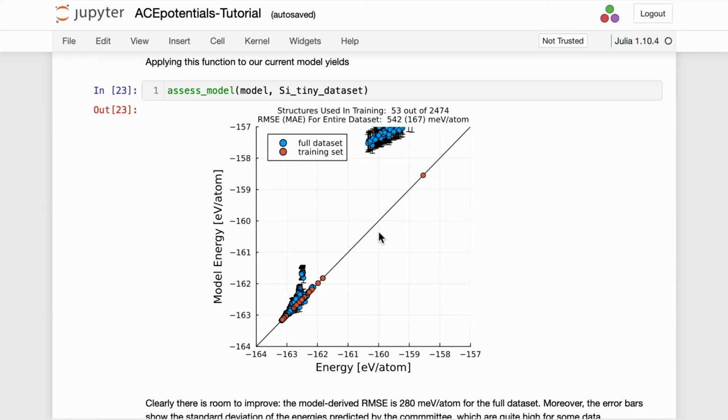Can I add something here? The way we're applying the Bayesian framework here, and the way almost everybody does it, is actually complete bogus. We're assuming that we have noisy data and then we ask how the noise propagates through the model. That is not what we have. We have data without noise. Yeah. But we haven't covered the whole space of possible things we want to predict. Right. So there's a huge leap of faith in all this, and I started talking to Yusuf about how to fix this.